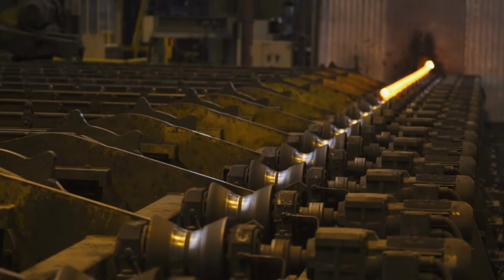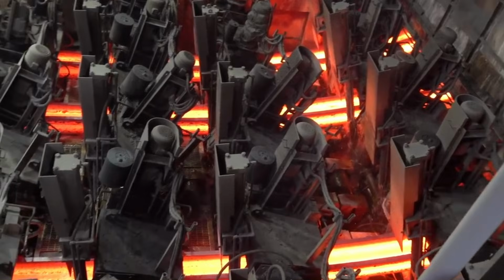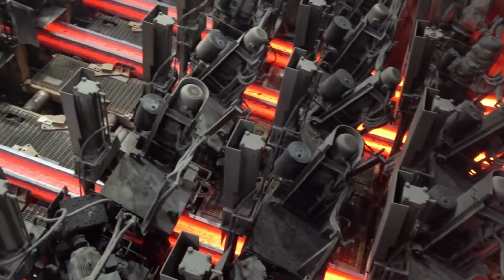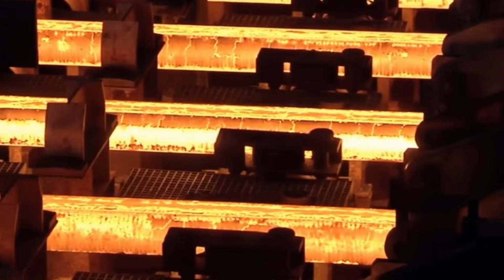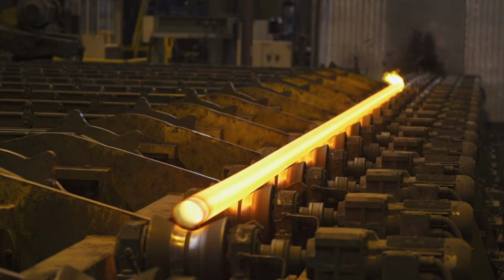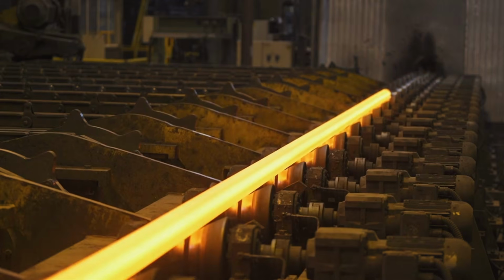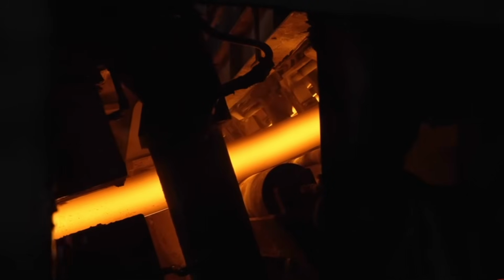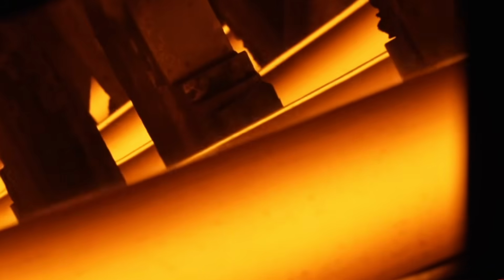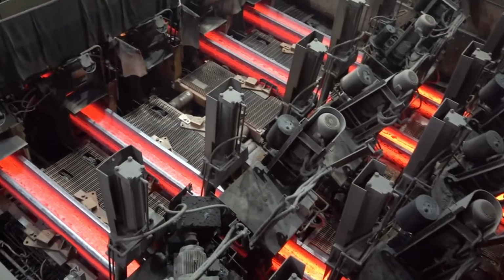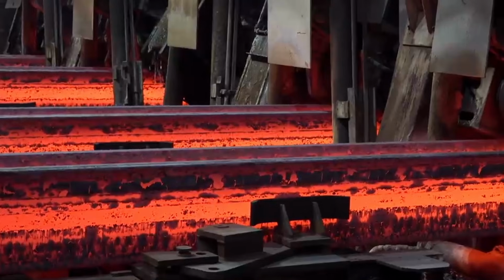The rolling mill is where transformation happens. A glowing billet enters where massive steel rollers squeeze down with thousands of pounds per square inch. The billet elongates and thins, traveling to the next stand, where rollers squeeze again from different angles. Modern mills contain 10 to 15 stands, and the journey from square billet to I-beam takes less than 2 minutes across over 1,000 feet.